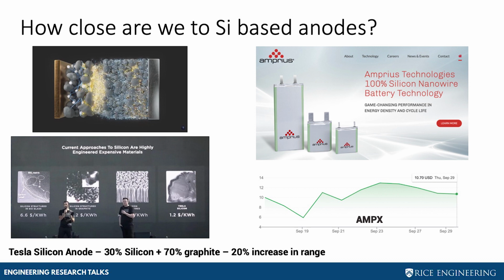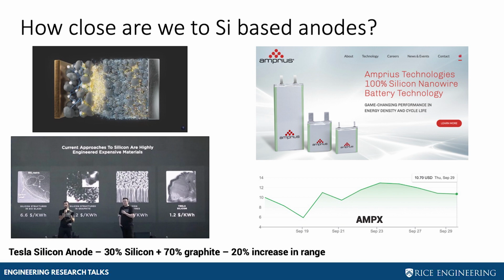And if we think about commercial entities that actually use it, here is Elon Musk at one of the big Tesla unveils, where they touted the Tesla silicon anode. This is one that has 30% silicon, 70% graphite, so they are making a composite here. And it has an increase of 20% in range for the Tesla. Another example is Amprius Technologies. This came from Yi Cui's group at Stanford, and they are advertising the 100% silicon nanowire battery. They just went public, and their stock price as of today was $10.70, in case you are inspired to go and invest.